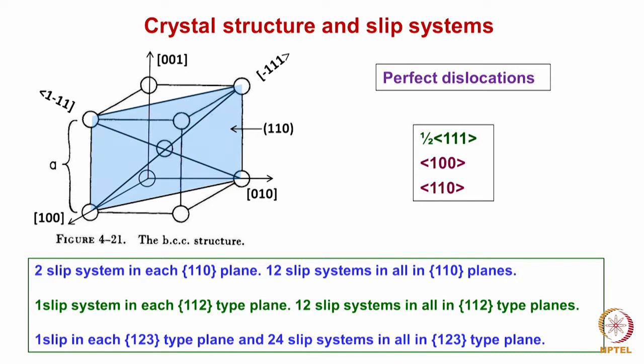That is the shortest translation vector, and it is also the close pack direction. In fact, in BCC there is only one close pack direction, which is along the 111 direction. This 111 direction can lie along essentially 6 110 planes. If we consider the number of slip systems, in each 110 plane there are 2 close pack directions, and 6 planes, so totally we will have 12 slip systems.